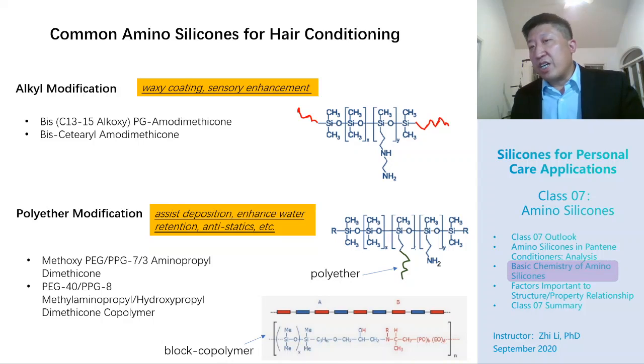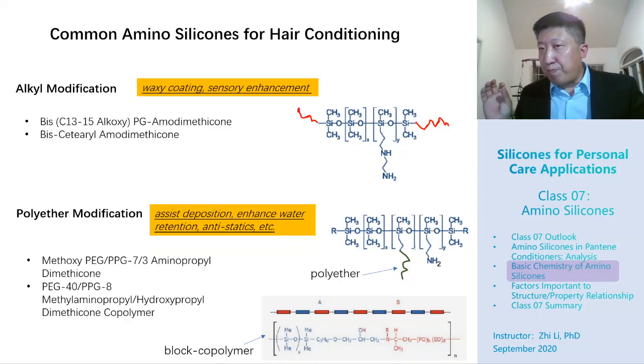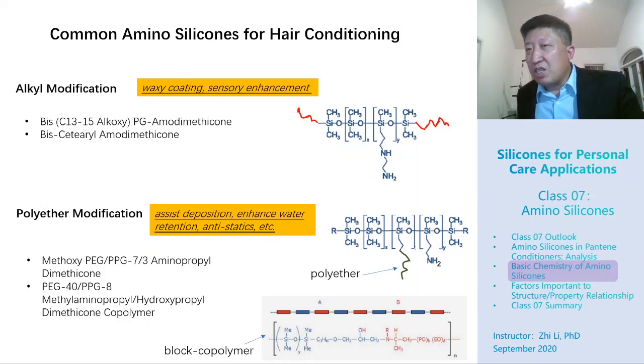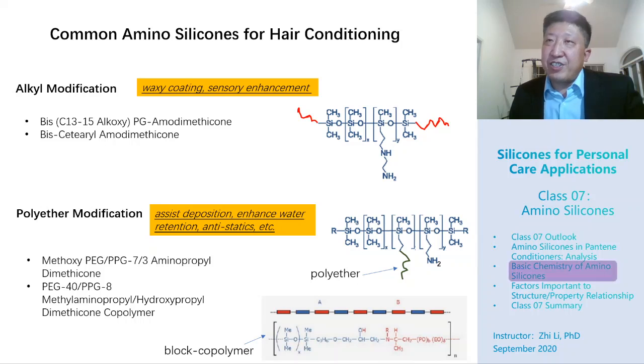While the damaged hair area becomes more hydrophilic and potentially negatively charged. As a result, this hydrophilic site in water is less likely to be coated by silicones if you do all this surface energy, surface tension calculation, trying to see the free energy difference when you study all the new surface area generated and the old surface area that disappeared because of the coating.